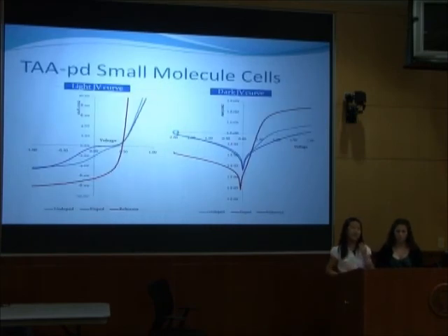However, when we actually incorporated the TAPD into small molecule cells, you can see that the results were not very spectacular. This is the reference cell, the control, and this is the actual doped TAPD layers. Because of this, we predict that the TAPD has very low charge mobility and will not work as a hole transport layer for an organic solar cell.